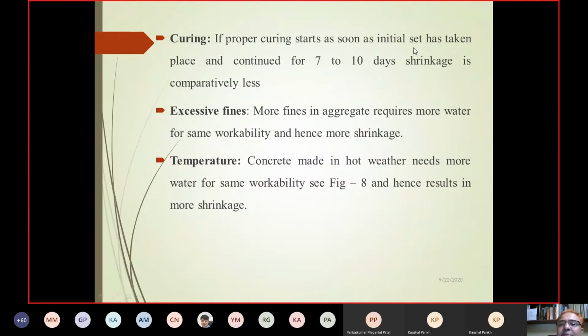Then curing: proper curing should start as soon as possible after initial set and continue for 7 to 10 days. What I suggest is, when we cast the slab, within 60 or 90 minutes we have to cover that slab with plastic sheets so that no moisture evaporates. In most cases, by the next day, moisture has gone overnight and the slab suffers. So I suggest that within 60 or 90 minutes we cover the slab with plastic sheet. Then excessive fines cause more shrinkage. Concrete made in hot weather needs more water for the same workability, hence the result is more shrinkage.